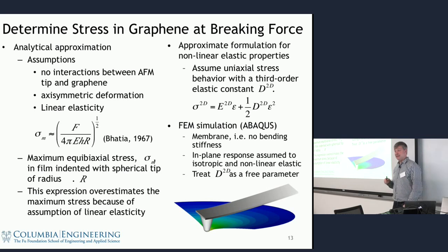And that's a kind of generic problem with a one-dimensional material. If you have a single defect, that's always going to be the weak link, always going to be the weak point. Or the clamp, same thing, because the tension is uniform throughout. On the other hand, if you have a 3D material, you always have a surface which is going to be weaker than the bulk, because the atoms at the surface are only bonded on one side. They have dangling bonds on the other. So you're always going to have some sort of weak point at the surface, and you're always going to have cracks that initiate at the surface and go to the center.